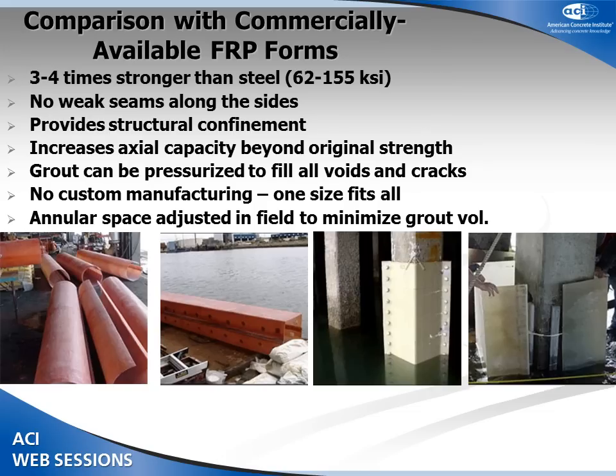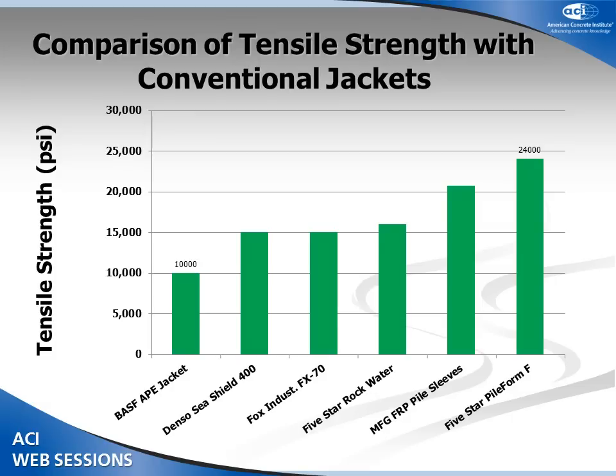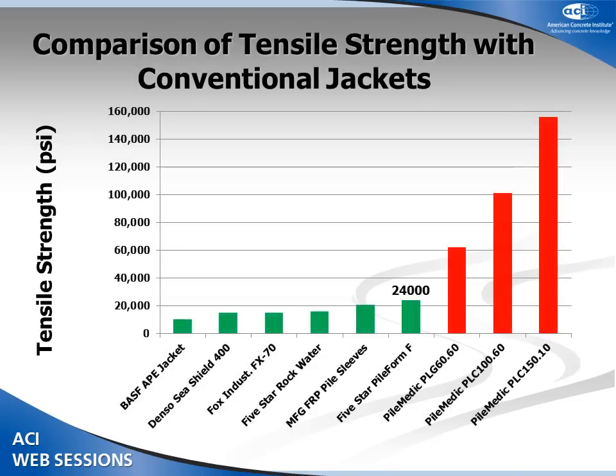Comparing this with other materials, it claims there are no weak seams in this material, the strength is very high, it does provide confinement as well as axial-flexural strengthening, and there is no problem injecting grout or epoxy. This need not be custom-built and has the flexibility of being used for different size and different shape columns. A tensile strength comparison — assumed to be coupon tests of the laminates — shows this material goes way beyond what's available in the marketplace, which is cited as one of the key advantages.